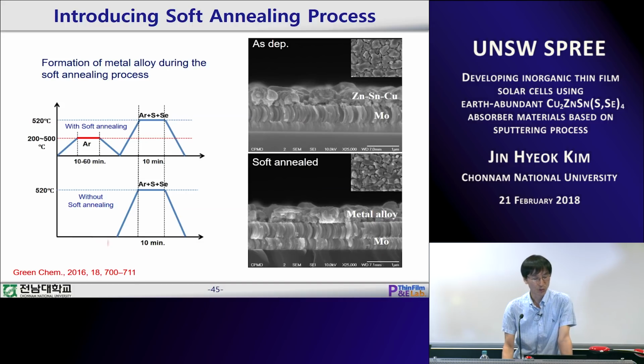So we introduce a soft annealing process like this. We vary the temperature from 200 to 500, and we hold at this temperature from 10 minutes to 60 minutes, and then see how the result changes. This is the as-deposited sample microstructure, a cross-sectional SEM image, and we see 3 layers. After the soft annealing process, we have an intermixed and more dense microstructure.